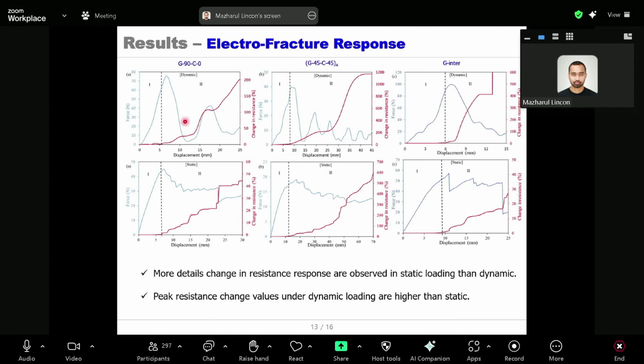Now, another basic difference between this dynamic and static experiment is, if you see the peak change in resistance, in this dynamic experiment all specimens' peak resistance change is very high. Here it's 200%, 1200%, around 400%, compared to the static. Static change in resistance is very low, around 40%, here 500%, and here 30%.